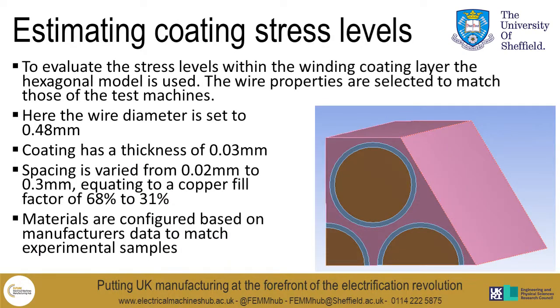So first off, we need to estimate the level of coating stress within the conductors during the thermal cycles. So to evaluate this, we produced the model which can be seen here. It's a similar hexagonal model to the one I've discussed previously, the main difference being that the wire diameter and coating thickness have been modified to match the test samples which were used in the experimental work.